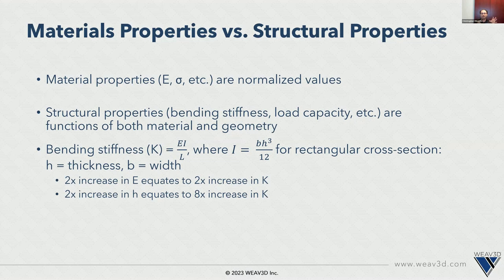So one of the simplest examples of this for bending stiffness is for a simple rectangular cross section, where the bending stiffness is a function of modulus E and I, which is the second moment of area. And that I is defined by the width of the part times the cube of its thickness. So what this effectively means is if you double your modulus and you keep the geometry the same, you double your bending stiffness. But if you double your thickness and you keep the material the same, you get an 8 times increase in bending stiffness. This is part of the reason why injection molded parts use ribbing, because it provides them with extra bending stiffness in a material efficient way to do it.